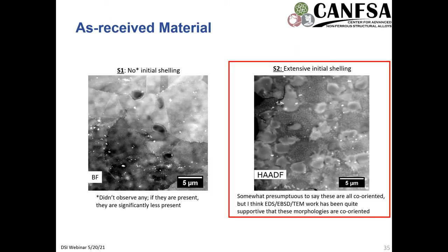So since we're able to demonstrate that the dissolution of the primary gamma prime is able to form a relatively stable gamma shell or neighboring co-oriented gamma region, we were trying to establish, is this gamma shell that's forming as a result of the dissolution of this primary gamma prime stable? So we took a region with extensive initial shelling that already existed, and we did a high temperature exposure for a long time hold to allow for an attempt to reach an equilibrium condition, to see if this gamma shelling that is occurring is really indeed stable.